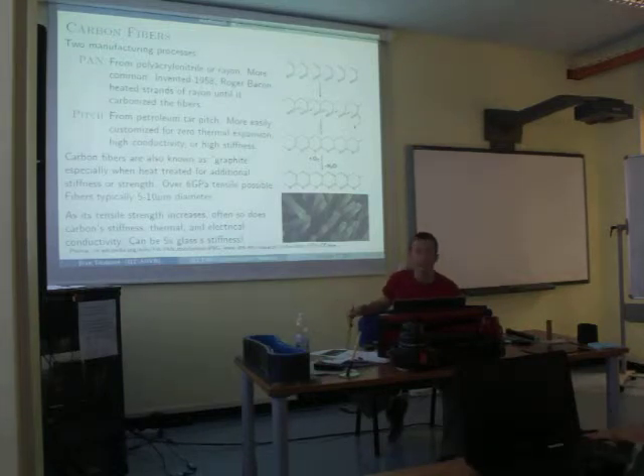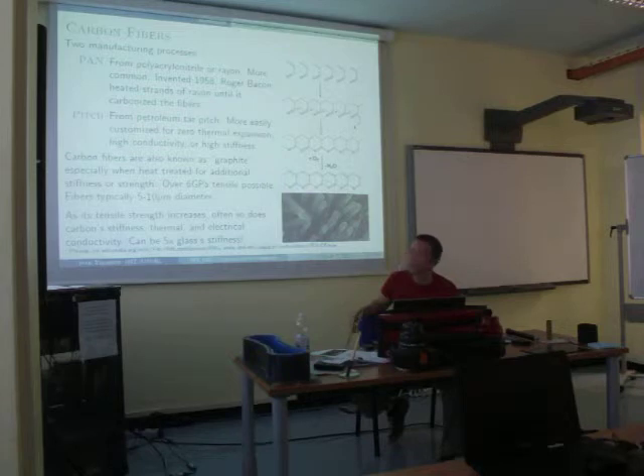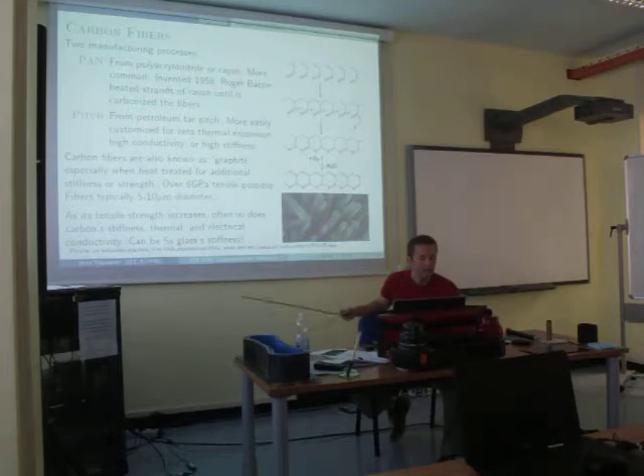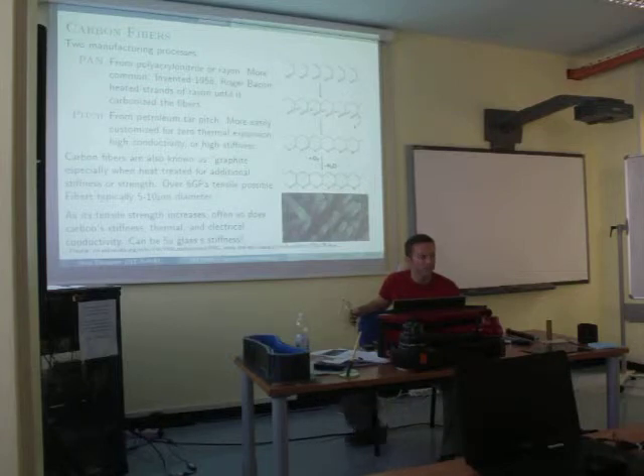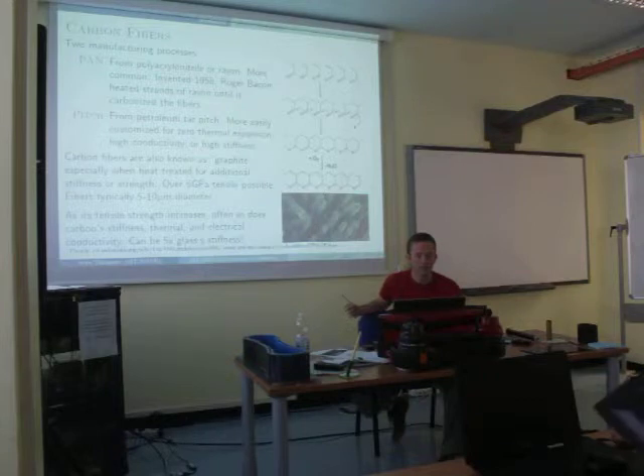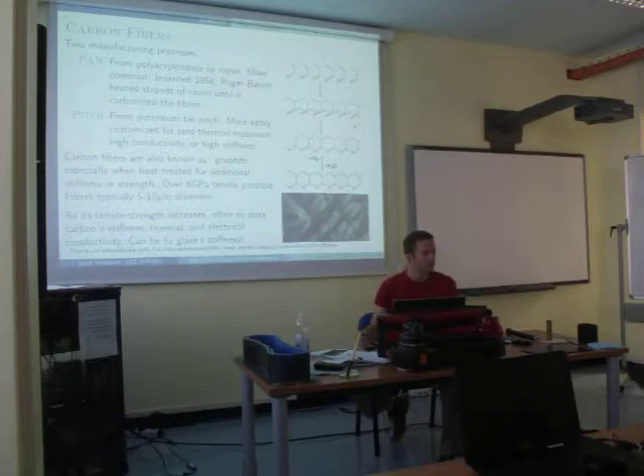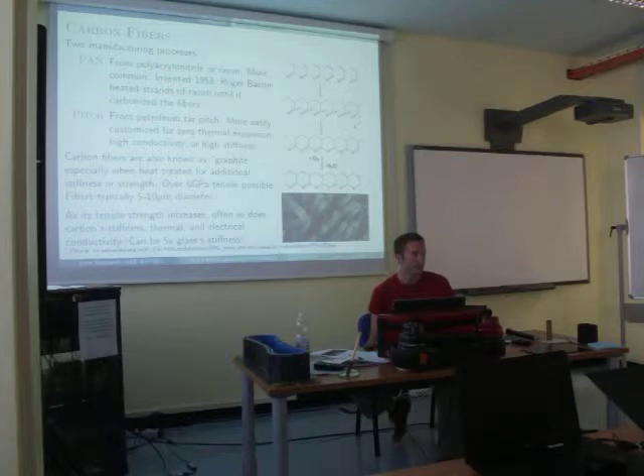They can be customized to have zero thermal expansion, so they're nice for dimensionally accurate parts, such as in jet engines. You can have higher electrical conductivity or heat conductivity. In fact, those two often go together. And much higher stiffness than with the PAN fibers. Carbon fibers are sometimes called graphite, especially when they've been heat treated after production for additional strength. And you can have up to about maybe 6 gigapascals of tensile strength. The fibers are about 5 micrometers in diameter, and these fibers can be about 5 times as stiff as glass, as fiberglass. As I just said, the stiffness, thermal, and electrical conductivity often go together. As you increase one, they'll go together. This is not true for the resins. The resins do not conduct electricity. The resins do not conduct heat very well. They're just plastics.